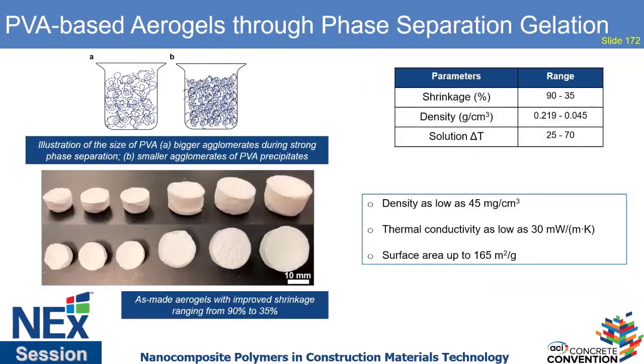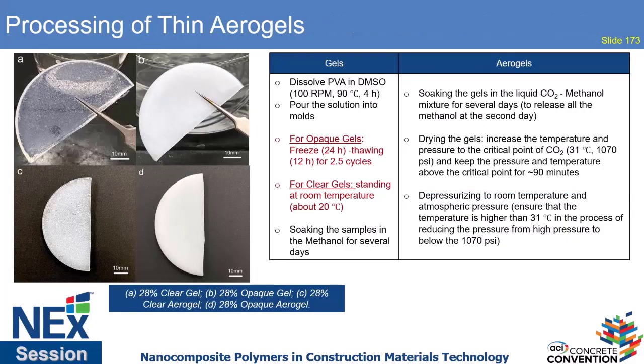And then the last thing I'll show you is the aerogel work that we've been doing. So we're using this phase separation technique in order not only to help disperse nanomaterials, but also to help us to form polymer gels that have very small domain sizes, because it helps us when you're supercritical drying aerogels in order to make the structure, and helps the shrinkage. So this is one example where we're making aerogels that are three-dimensional puck-like structures, and we're trying to reduce shrinkage. But we're also making them in thin film structure, where we can make them opaque or we can make them clear, just depending on the processing.